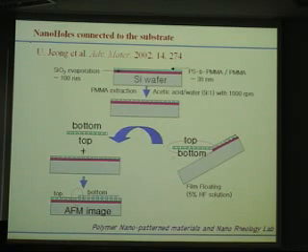In order to confirm the holes, or to expose the bottom of the film, we use a simple technique. First we evaporate silicon oxide, about 100 nanometers. Then HF removes the silicon oxide.